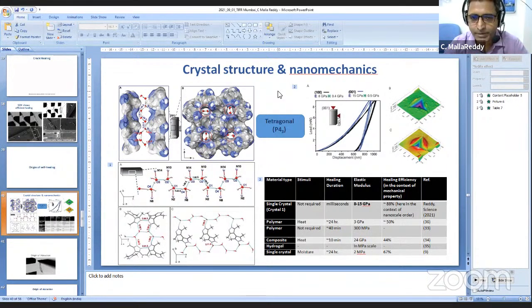Definitely, I think there will be some influence, because people have shown that even in a centrosymmetric crystal, if you dope with certain non-centrosymmetric materials, you would still see some kind of polarization response. So you can always disbalance and break the symmetry, and then you can make the materials a little polar. So I think definitely some of these will be interesting things to do.